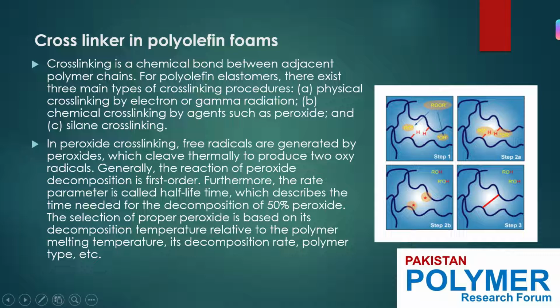In peroxide cross-linking, free radicals are generated by peroxides. You can have a look at the picture mentioned here, which cleaves thermally to produce two oxyradicals. So free radicals are generated over here, and those free radicals contribute to making a three-dimensional structure. Generally, the reaction of peroxide decomposition is first order. Furthermore, the rate parameter is called the half-life time. It's the basic chemistry which describes the time needed for the decomposition of 50% of peroxides.